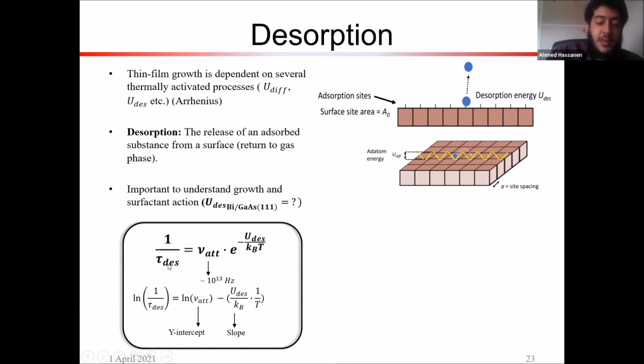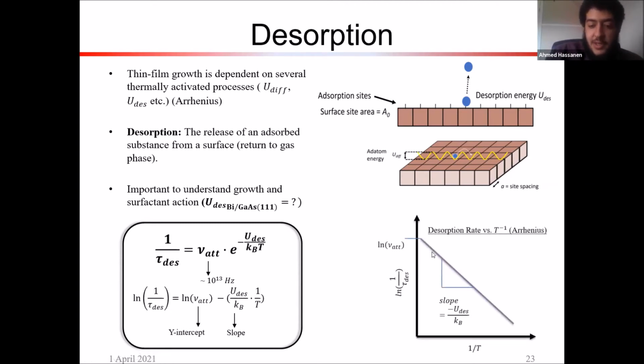Basically this is an Arrhenius relationship. There's a relationship where tau desorption, the desorption lifetime, is equal to this attempt frequency, which is the frequency of bouncing the atom, trying to get rid of the bond, times a term that's dependent on the temperature and the barrier energy. If you take the log of both sides, you can start to see that we can get a linear Arrhenius plot, of the ln of the desorption rate versus the inverse of the temperature. We can then extract the slope, which is the desorption barrier. So if we manage to calculate tau for different temperatures, we can do this plot and extract the slope, which is the desorption energy, which is our goal.